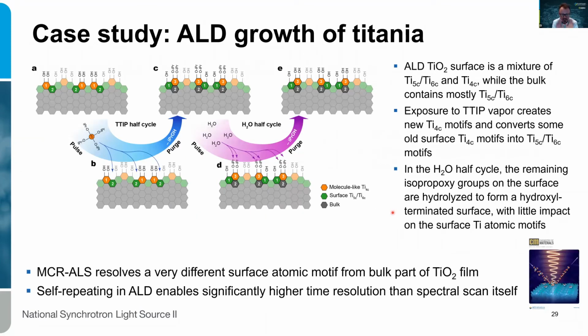All right, and based on this, I don't want to go into the mechanism so much, but it essentially tells us the sequence of events that happen during the half cycle of the precursor and the half cycle of the water addition. Nothing from the titanium perspective happens in the water cycle. It's just that the ligands are being removed. But it really shows how this advanced processing and data analytics helps you to resolve those atomic structures that only occur transiently during the process. But of course, it's because of the self-repeating nature of the process that allows us to do that.